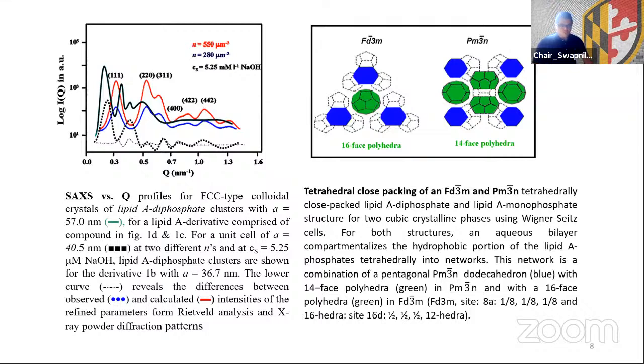This figure shows small angle X-ray scattering profiles versus scattering vector Q for the FCC type colloidal crystal of lipid A diphosphate cluster with A 57 nanometers, and for the derivative composed of 1D and 1C shown in figure 1. For a unit cell of A of 40.5 nanometers and 2 different ends, this will mean different subunits at a concentration of salt of 5.25 millimolar sodium hydroxide. With these results, we can go to the composing the assembly to a tetrahedral close packing of a face centered cubic lattice Fd3m and simple cubic lattice PM3N, and where the tetrahedral and close packed lipid A diphosphate and lipid A monophosphate structure for 2 cubic crystalline phases using Wigner-Seitz cells.